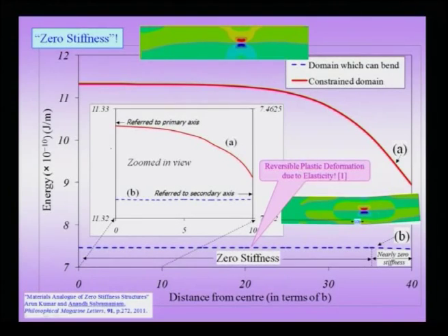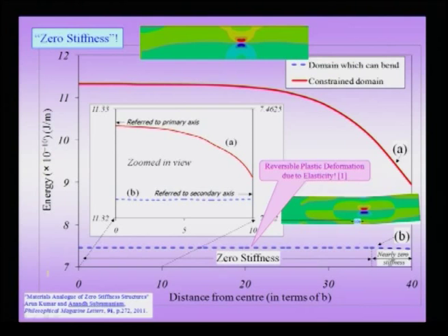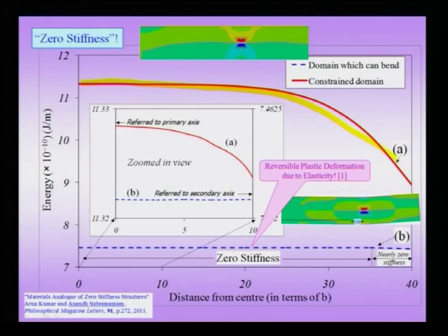Now, an additional interesting thing is that normally, as we pointed out in the previous case, when you have a dislocation, it feels an image force towards the free surface. That means that suppose I take a crystal and plot the energy of the crystal as the dislocation is positioned towards the free surface, the energy would decrease as shown by a curve like this. So, it is decreasing always, and finally of course, when it leaves the crystal it creates a step.